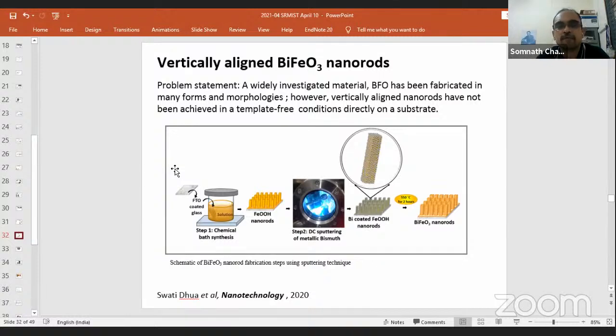We thought of one innovation. Earlier, in my postdoc, I was working on iron oxide nanorods. Iron oxide nanorods we prepare in a much simpler way than electrochemical anodization. We prepare them with just chemical bath deposition. You have iron chloride solution, you put some conductive glass inside, you keep it at 95 degrees, mind it, 95 degrees. You do not let the water mixture boil, 95. And then these nanorods grow from the FTO substrate. Okay. Now, I left it at that point, FeOOH nanorod.